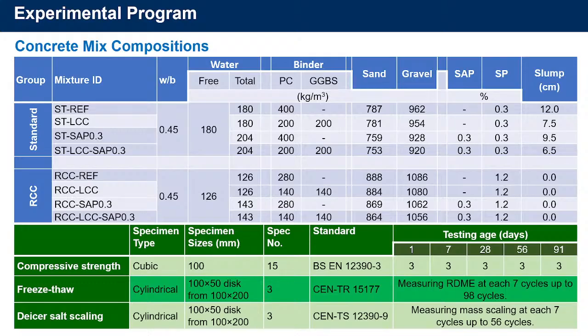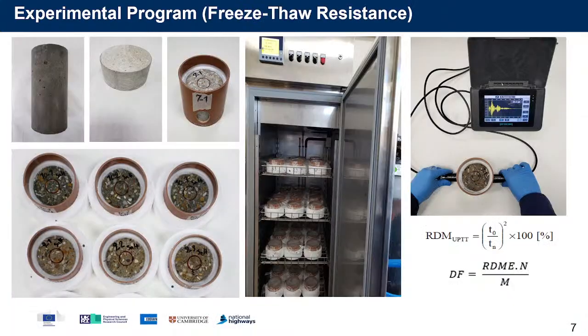As you can see, the water binder ratio in all mixes has been constant at 0.45. Due to the water absorption capacity of the superabsorbent polymers, I have slightly modified the water content in the SAP-modified concrete mixes to ensure that the effective water binder ratio remains constant. In terms of the experimental program, I measured the compressive strength from 1 day to 91 days, and the freeze-thaw resistance at every 7 cycles, up to 98 cycles without de-icing salts and 56 cycles with de-icing salts.